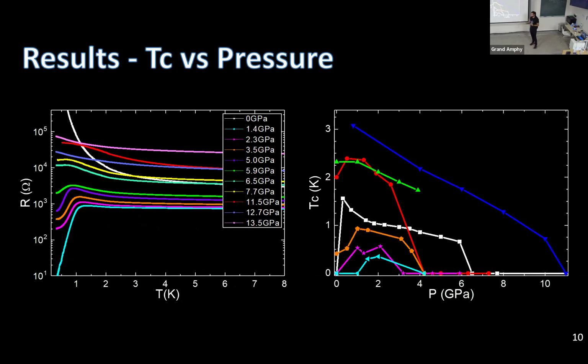Those are two competing effects. First, we are increasing the superconductivity. We can see that at ambient pressure we have critical temperatures spanning from 0, which indicates we're in the insulating regime, up to 3 Kelvin. When we start our experiment, first we see an increase in the critical temperature, an enhancing of the superconductivity, but after a certain point, a limit around 2 gigapascal, the pressure starts to destroy superconductivity. We go back down with the critical temperature up to a point where we go back to 0 critical temperature, indicating we are once again in the insulating regime.